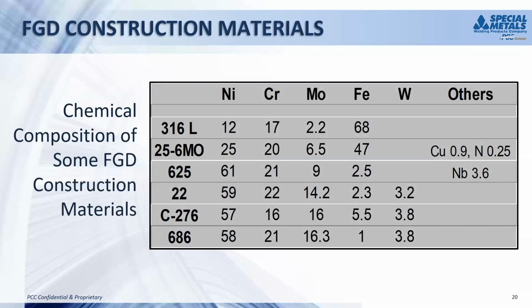The next slide shows some of the chemical compositions of some of these materials that are used. I would draw your attention to the molybdenum content. For resistance to localized corrosion, usually it's the molybdenum content that determines the corrosion resistance of the material. So if you compare something like 316 stainless, we saw the scrubber vessel that had corroded very quickly. With only 2% molybdenum, it doesn't have a lot of corrosion resistance to localized attack.